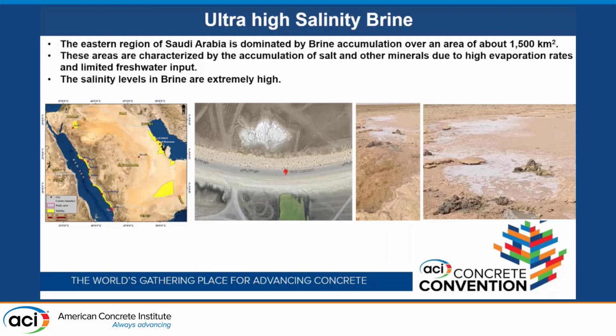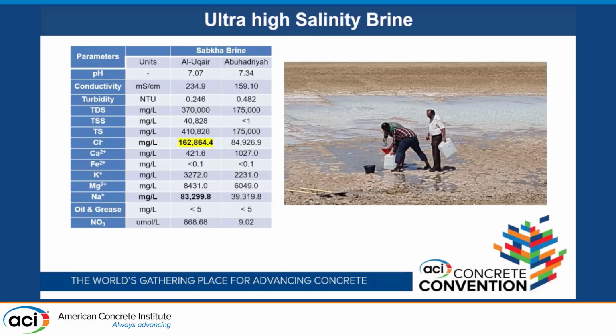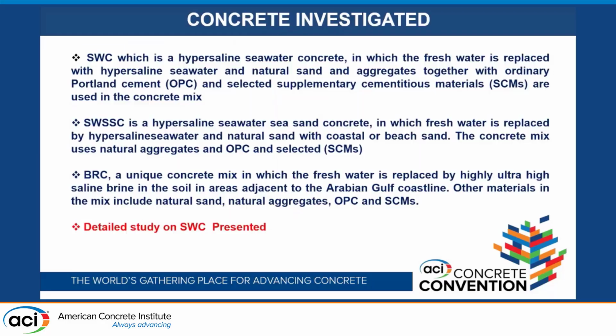And these are characterized by the accumulation of salt and other minerals due to high evaporation rates and limited freshwater input. The salinity level in these brines is extremely high, and you can see that over here as highlighted, 162,684. Very high salinity, 4 times that of the normal concrete. And on the right, you can see at many locations near the coastline of that region, you will see water coming up. You can collect that, and that is very highly saline brine. And in a large area, just a few inches down, you'll get this water.